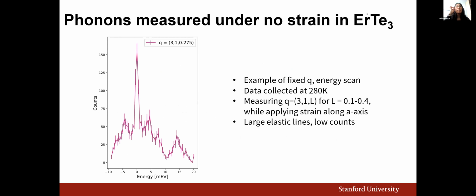Okay, so on this slide, I just have an example of a spectrum that we collected. And in it, you can see a lot of the issues that I pointed out in the very beginning of this talk. So this was for measurements when we are measuring along the C-axis while we apply strain along the A-axis. And this is not quite at the CDW wave vector. The CDW wave vector is about 0.3, so we're just looking a little bit off that Q value at 0.275. And so you can see, yes, these scans reveal that we have a fairly large elastic line, and overall our counts are low, probably due to the fact that I mentioned that the sample dimensions that we're working with are not quite optimized for large transmission of our signal.